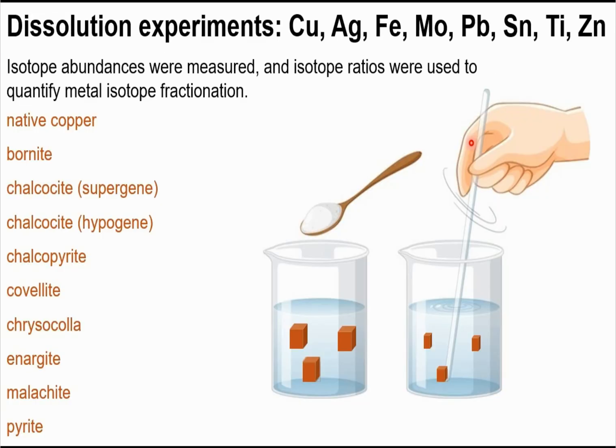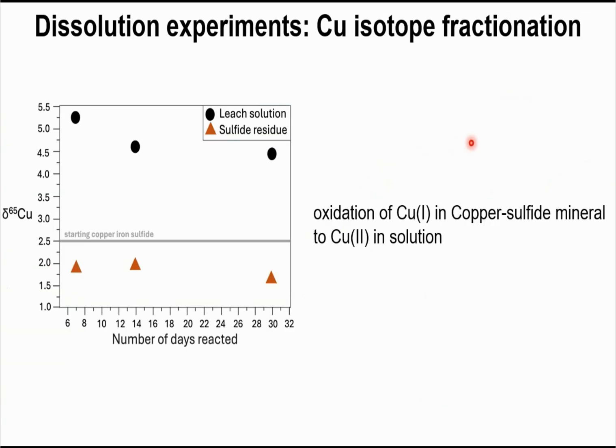So we did a lot of experiments in the lab. We took all of the copper-bearing materials on the left side of the screen. We did simple experiments where we reacted them with water, and then we measured the stable isotope composition of the residual sulfide after chemical weathering and the solution after it had chemically weathered with the sulfide. And we measured copper isotopes, iron isotopes, tin isotopes, moly, lead, zinc, titanium, you name it. If it's in the periodic table and it's got multiple stable isotopes as a metal, we measured everything to see what matrix we might be able to come up with to identify signal from noise.